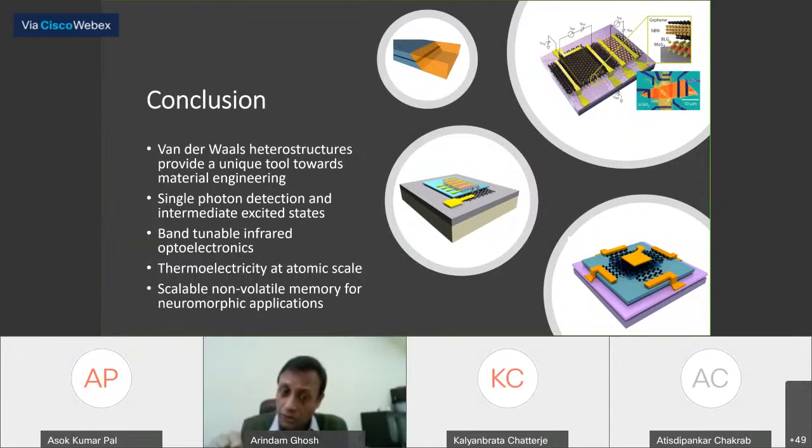Not only can the structures be unstable structurally, but they can also be extremely sensitive to environment, gas. For example, molybdenum telluride is a very interesting material because it has very small band gaps, so it can be used for microwave and infrared detection. The moment you take it out into the environment, it becomes unusable.